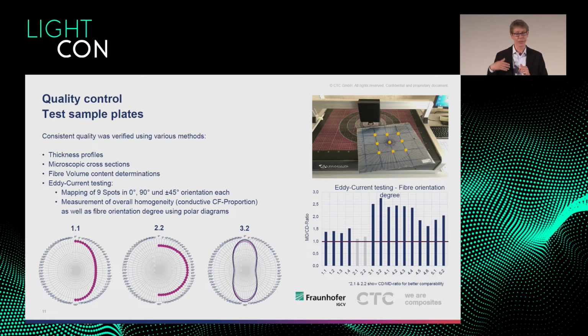And just to see if we can confirm that by NDT, so with non-destructive testing of these materials, we did eddy current testing and physically measured the fiber orientation, just to see if we can match NDT values with the values from when we chemically dissolve these materials and do all the destructive testing.